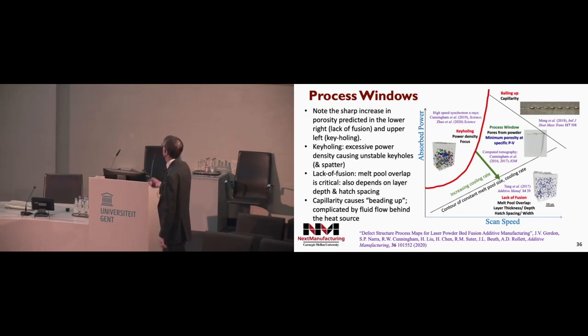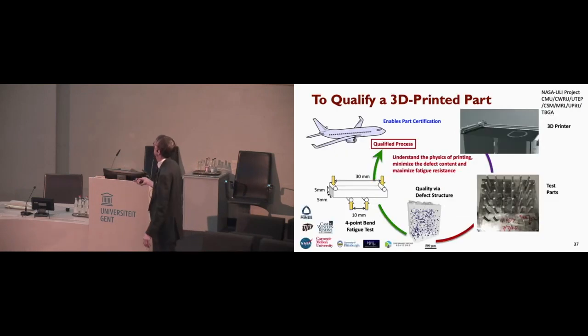And it's a problem because we really would like to keep on going up in power and in speed all at the same time. But the trouble is the melt pools stretch out. You have finite thermal diffusivity, and the longer the melt pool gets, the more unstable that can become, in addition to the instability in the keyholes. So that's the really quick summary of process windows.